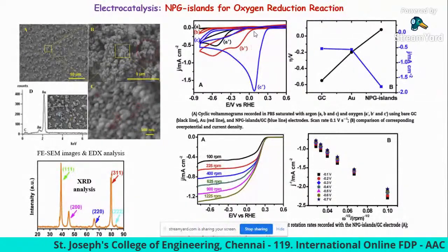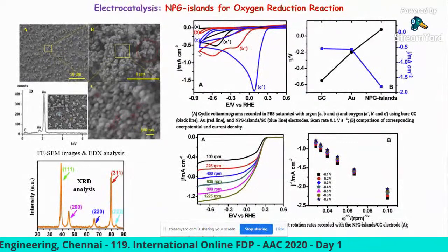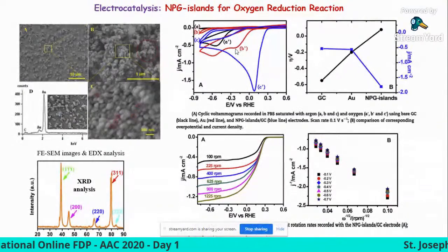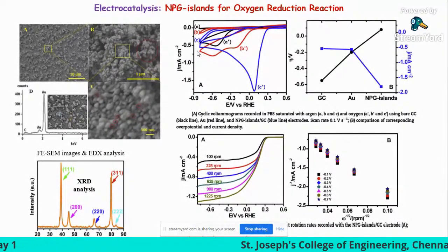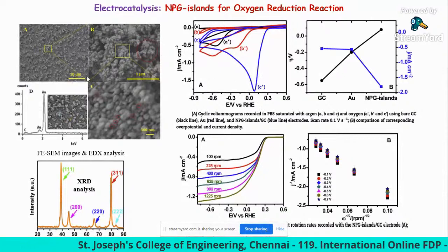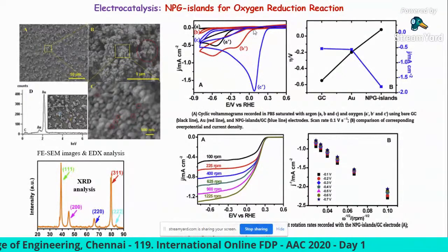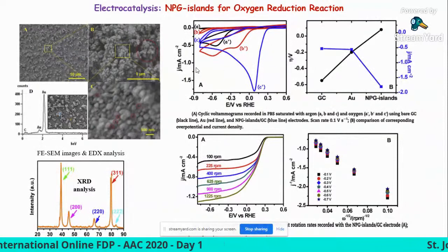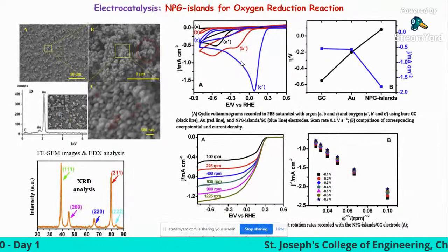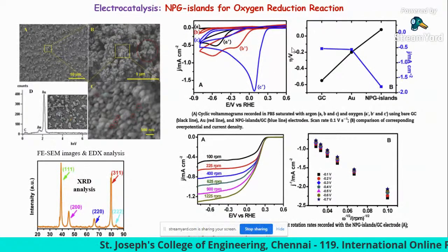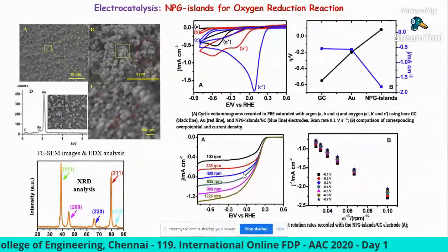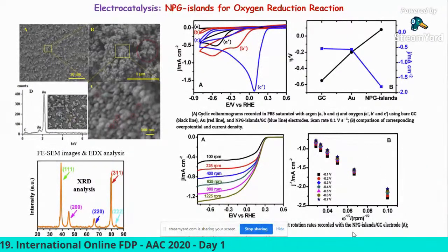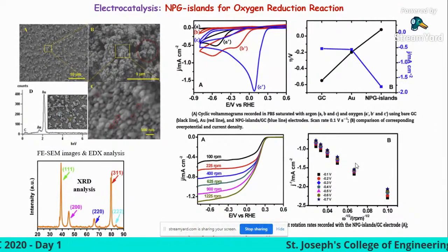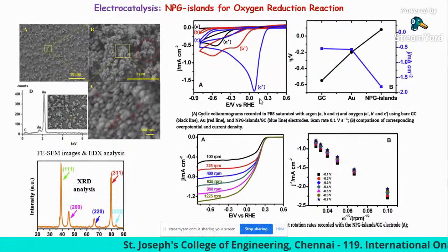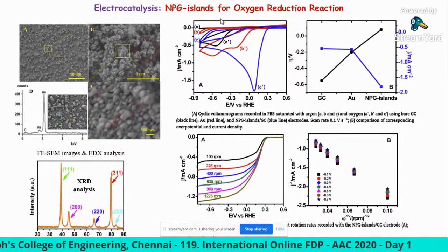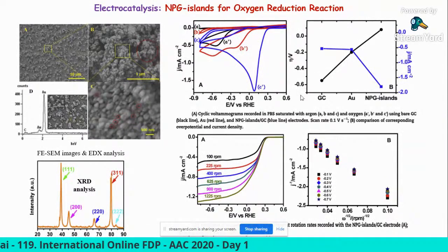If you have a poor electrocatalytic catalyst, then the 2+2 electron reduction takes place, where oxygen is reduced to hydrogen peroxide, and then hydrogen peroxide is further reduced to water. Our catalyst is a very good catalyst, so the direct 4-electron reduction takes place. That means the oxygen is directly reduced to water. How did we confirm that the direct 4-electron reduction takes place? To confirm that, we performed RDE experiments. From this, we used the KL plot. From the KL plot, we calculated the number of electrons, which is around 4. This clearly confirms that the fabricated nanoporous gold islands are a good catalyst for direct reduction of oxygen to water.